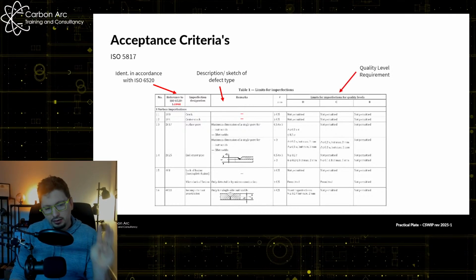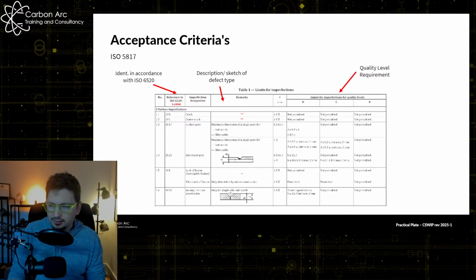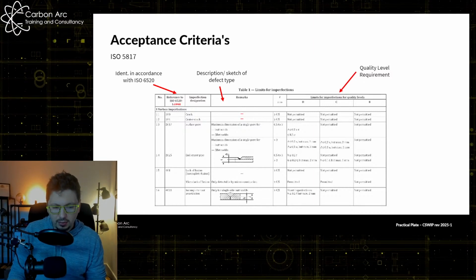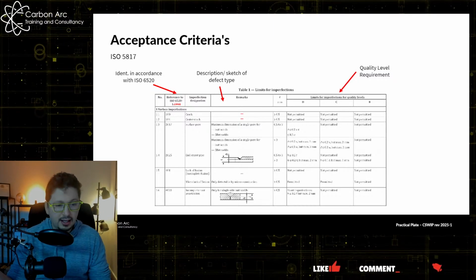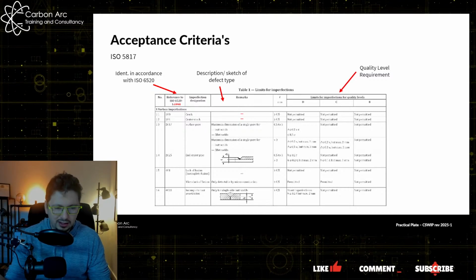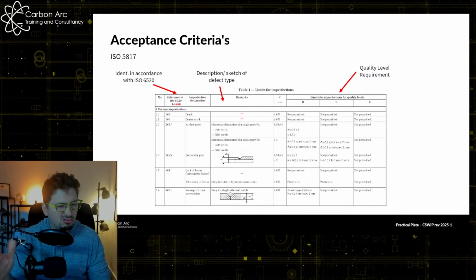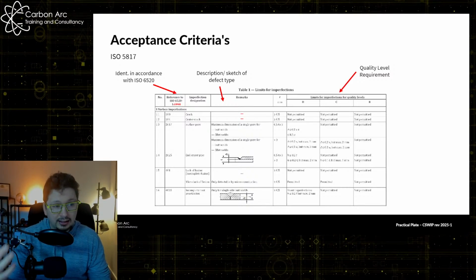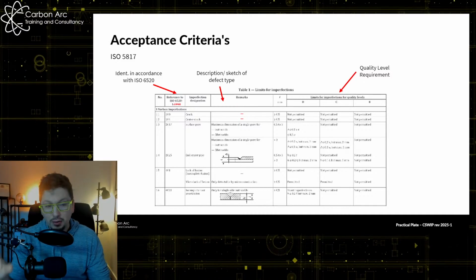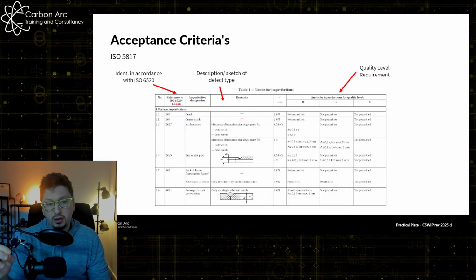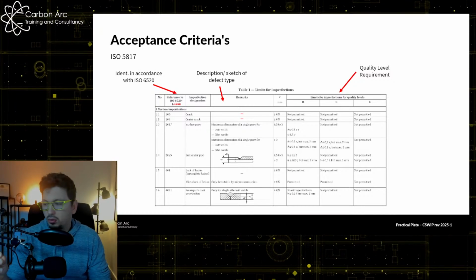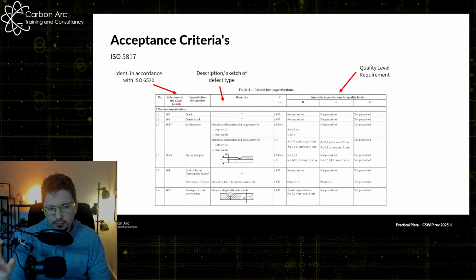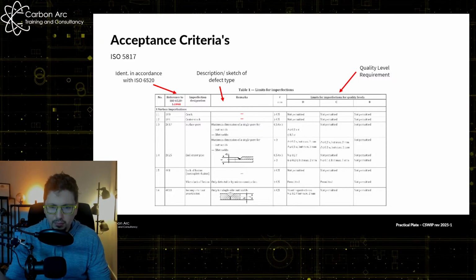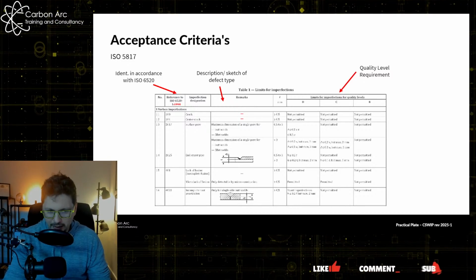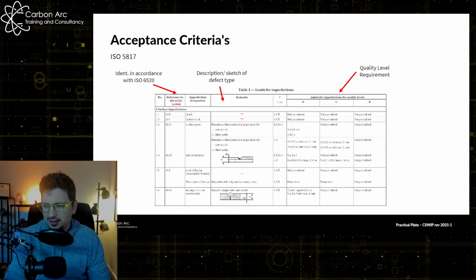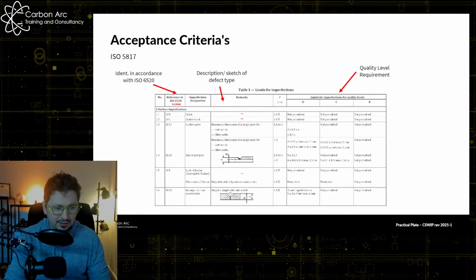We've then got our 3 levels of quality limits. In 5817, we have class D, C, and B. So D is like, I wouldn't even bother looking at it if it was a class D. Class C is generally okay. B is our highest level of acceptance criteria within the standard. But often a lot of client specs work to things which are like B+. So B plus additional things that tighten it up a little bit more. But we can see on the screen here, we've pretty much got level B, everything's not permitted. Level C, some things are not permitted. Level D, most things are permitted with a bit of tolerance.